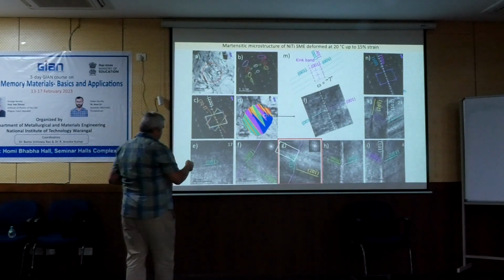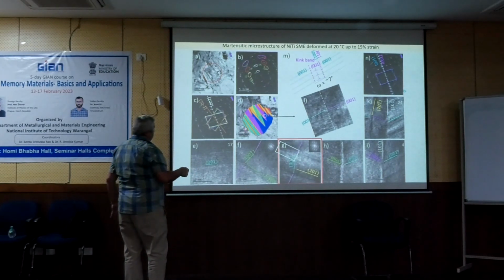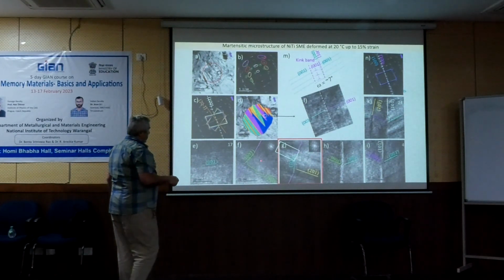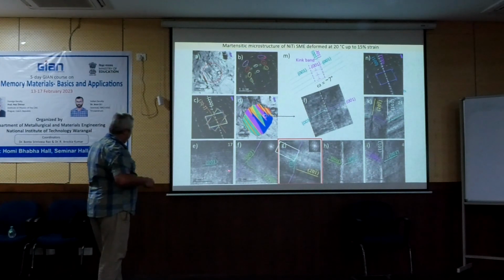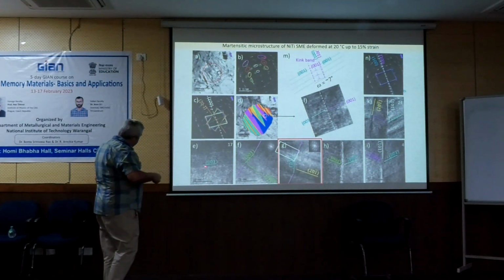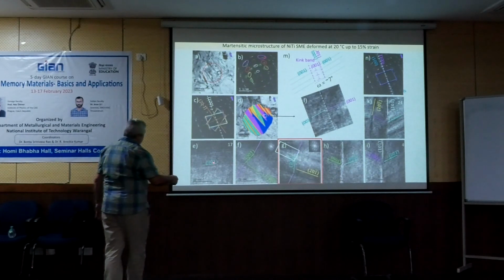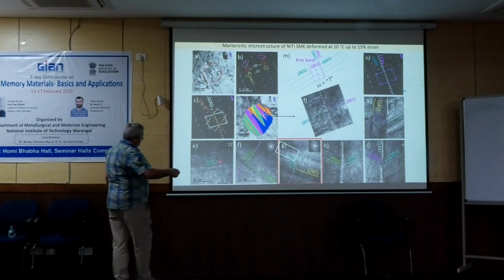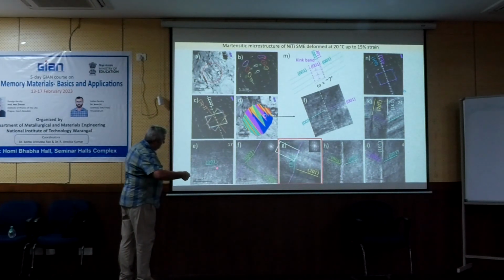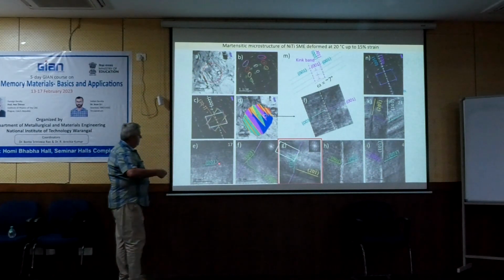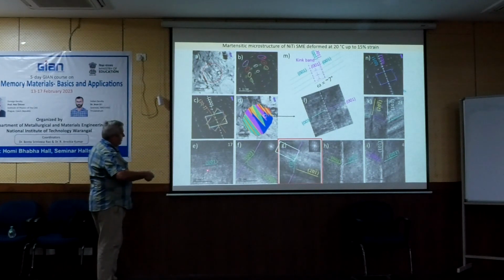So we can go even into the high resolution mode, and we can look how the martensite lattice is organized along the interfaces. And if you see here, you see some lattice planes. So for example, this is this compound twin, and here you see the lattice planes, and the lattice plane here is parallel because this is the characteristic of the compound twin.